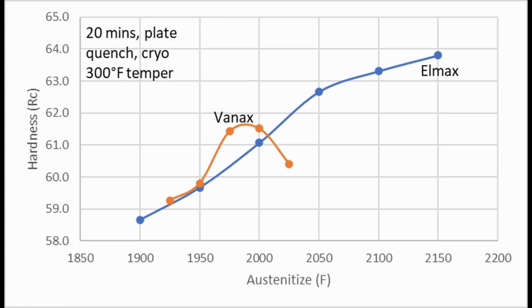The range for Vanax to be over 60 or 61 is much narrower. So 1975 to 2000 degrees is the peak hardness, but already at 2025, the hardness has dropped. Where the hardness drops is an indication that we have too much retained austenite. So all of that retained austenite is what is dropping our hardness. So Vanax is very difficult to heat treat to 60 plus Rockwell while also avoiding excess retained austenite.